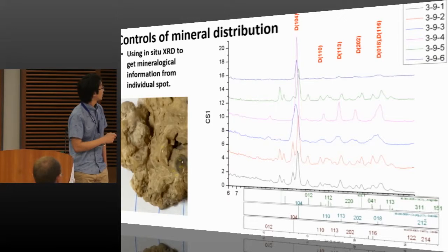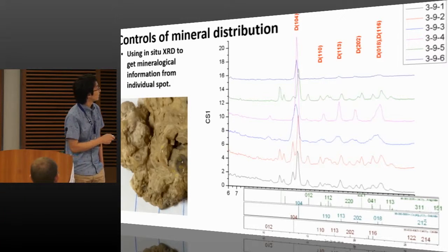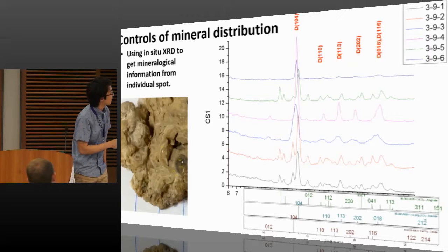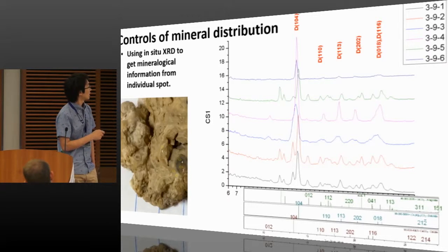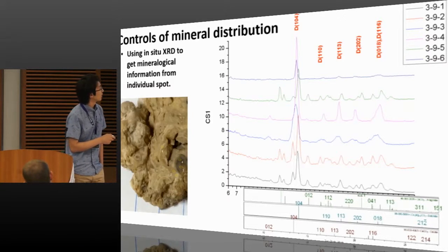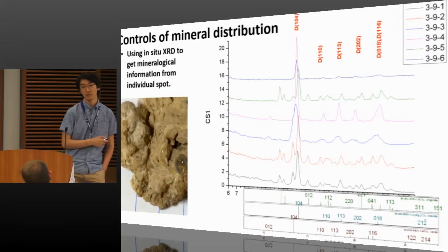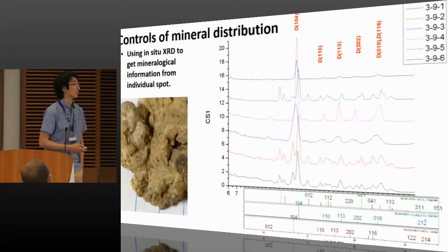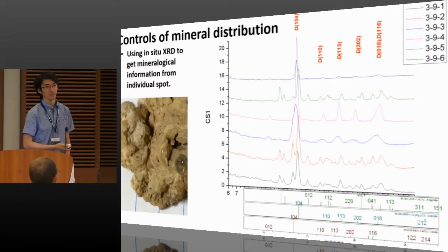So you can see points 1, 2, and 5 are like this, and they have tons of aragonite, calcite, and dolomite peaks in them. But in the dark area, points 3 and 4, all you can see is just dolomite. You can't find aragonite and calcite in it. Probably some high magnesium calcite, but mostly dolomite.